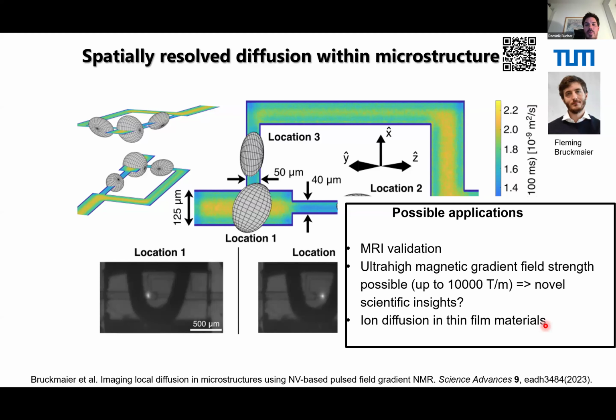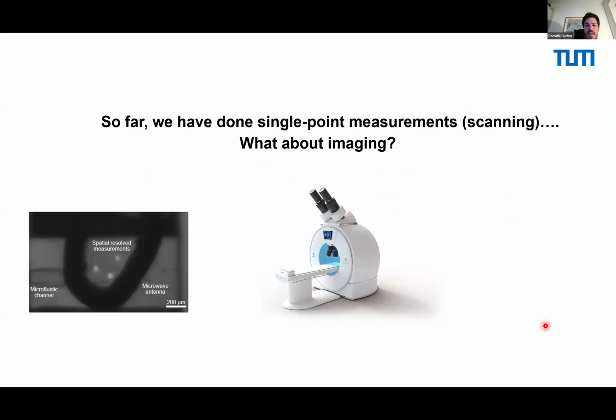Okay, so this is our diffusion MRI device. And of course, you can ask now, we did here a scanning approach. So we moved around our laser spot, we measured here, then we measure here, and we measure here. And of course, if you think about optics, the question is, why can't you just detect everything on a camera? Because in contrast to the scanning approach, you could do a widefield approach, and you would get all the information at the same time, in particular for NMR, where all of these measurements take a while. So that's exactly what we developed.